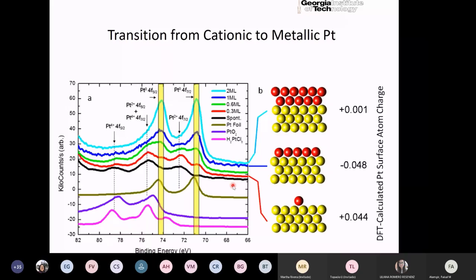Now, the other part of your question is about epitaxy. Epitaxy means that you have a lattice to lattice interaction between these two materials. And in order to study that, you don't need to have an imaging tool. For example, I showed you this EXAFS, extended X-ray absorption fine structure results, where we are looking at the local atomic structure around platinum. And what we saw was that the platinum-platinum bond distance, on average, was getting shorter. This is that compressive strain that is imposed by the graphene. And that is only possible if the graphene and the platinum have a lattice-lattice interaction and you have epitaxy. Okay, so indirectly you get the information about epitaxy.